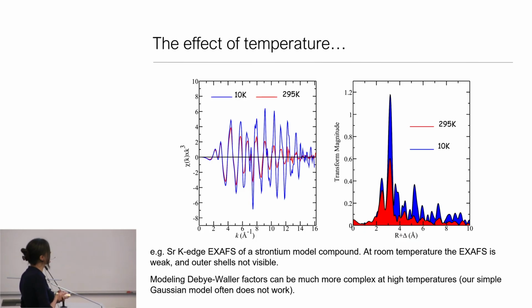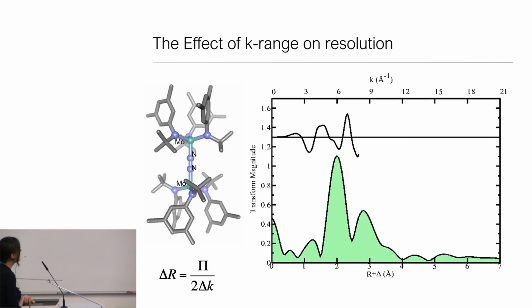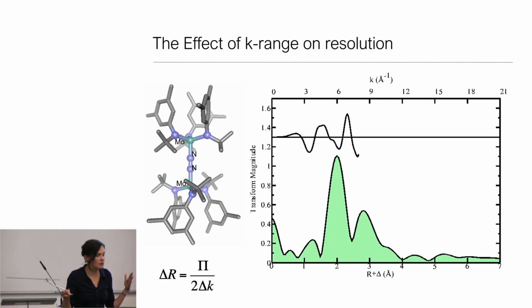The other thing you can see is I can get EXAFS much further out in K space when I'm at lower temperature. So the question is, why do I care about this high K data? That's because the further I go out in K space, the higher the resolution of my experiment. Roughly speaking, the resolution of an EXAFS experiment goes as pi over 2 delta K. That means if I want to separate two similar scatterers that are only 0.1 angstroms apart, I need data out to roughly K of 20. That's fairly rare to get. So most of the time we talk about similar scatterers within 0.15, 0.18 angstroms needing to be grouped together, increasing my static disorder. Okay, so that is an intrinsic problem.